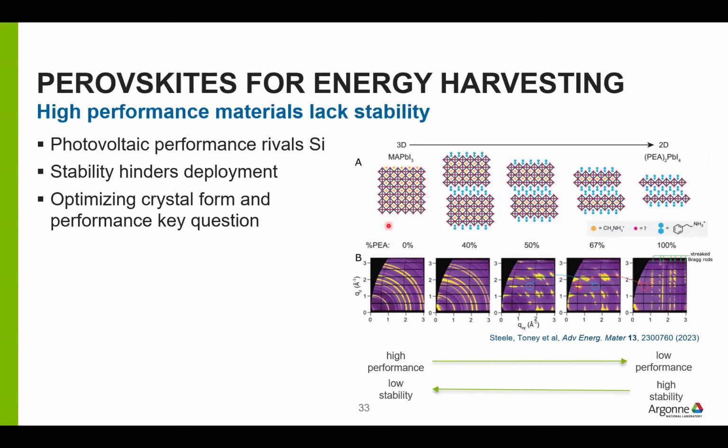And the perovskites can be in 3D crystals or 2D crystals like this, where there's a single layer of these octahedral groups. Or in between, you can have a mixed 2D/3D with a different variety of layers in between. So this is n equals 2, n equals 3, n equals 4. These are called mixed 2D/3D, or sometimes just loosely 2D materials in between.